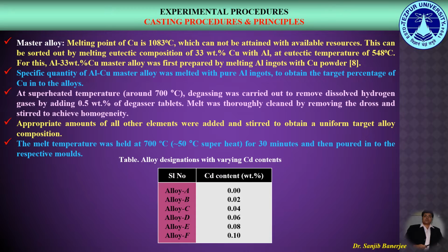In the present work, 2219 aluminum copper alloys were processed by standard casting technique. The alloys were microalloyed with varying contents of cadmium, and the cadmium contents in the alloys varied from 0 to 0.1 weight% as shown in this table.